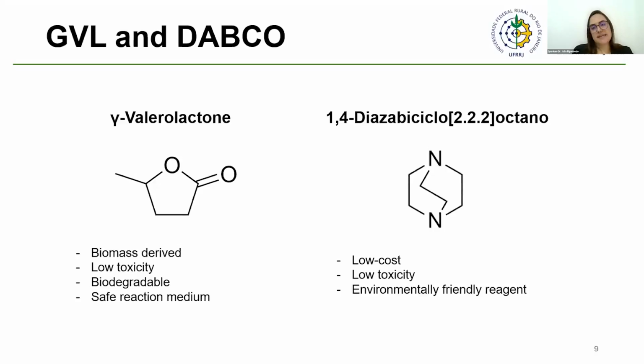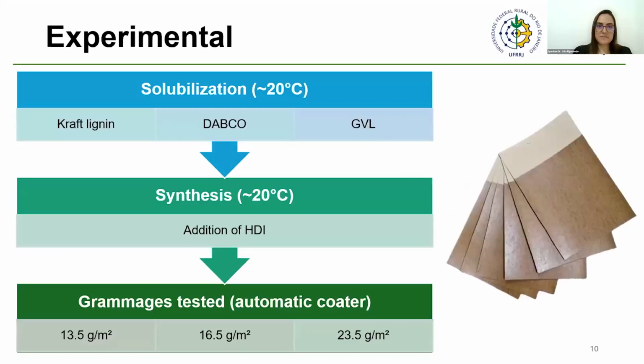And to improve the lignin reactivity, the lignin was solubilized in GVL, gamma-valerolactone, which is biomass derived, has low toxicity, and is biodegradable. And to catalyze the reaction, we used DABCO, which helps control the reaction and improve the final product quality. The advantage of DABCO is that it's low cost, has low toxicity, and is a more environmentally friendly reagent.